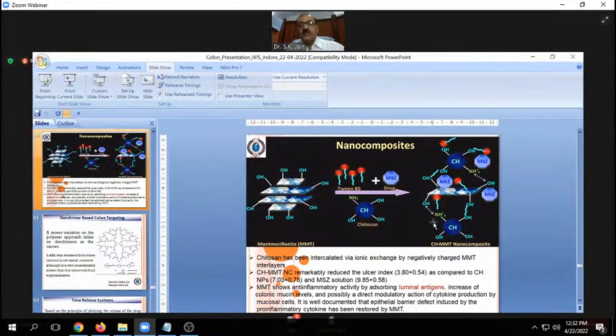This is a very new nanocomposite. One of my PhD students prepared this nanocomposite, so we filed a patent also. Here we prepared a layered nanocomposite. Chitosan has been intercalated by ionic exchange with negatively charged montmorillonite, right? So Chitosan montmorillonite nanocomposites remarkably reduce the ulcer index to 3.8 as compared to the Chitosan nanoparticles, which have 7.03, and mesalamine, which has an ulcer index of 9.85. So we can see that it is 3 times as effective as compared to mesalamine.